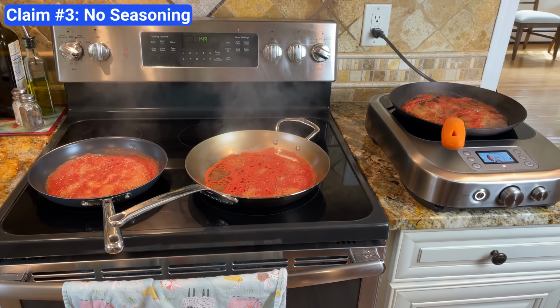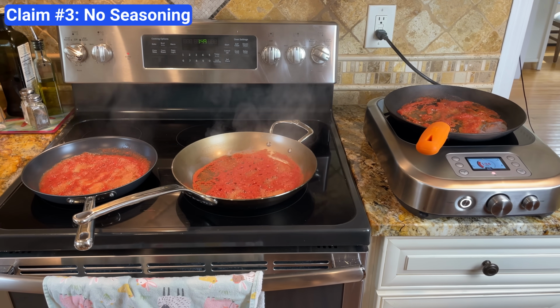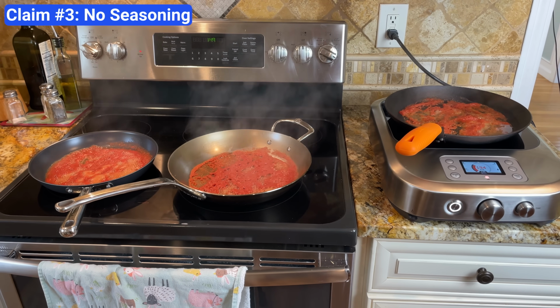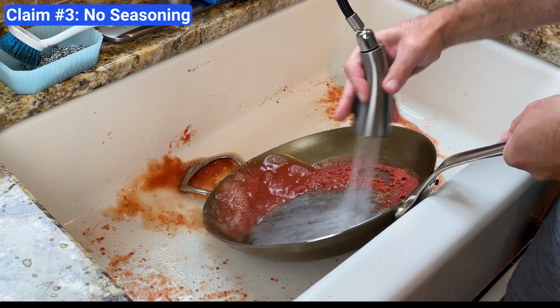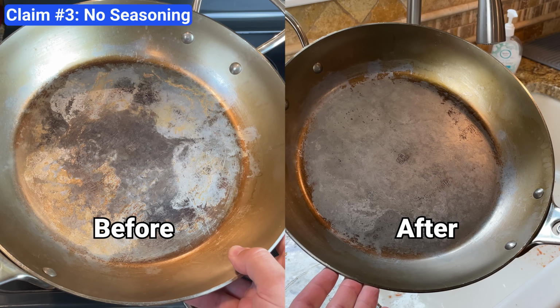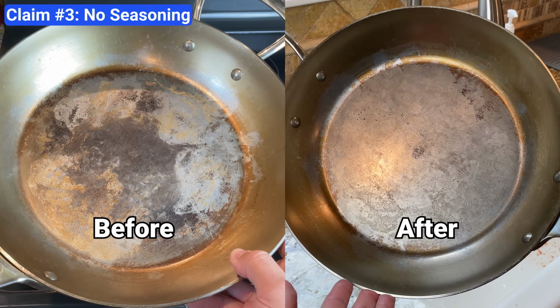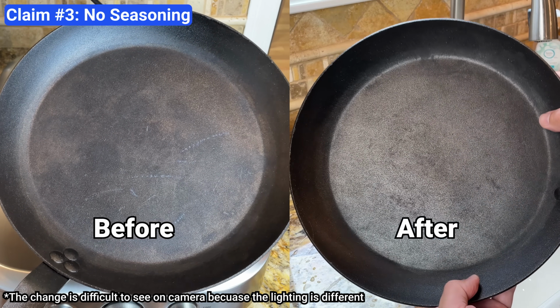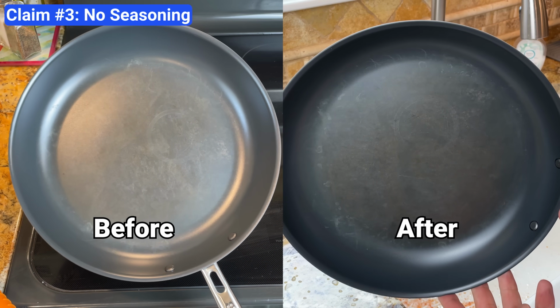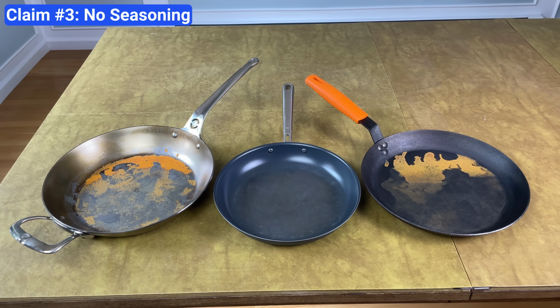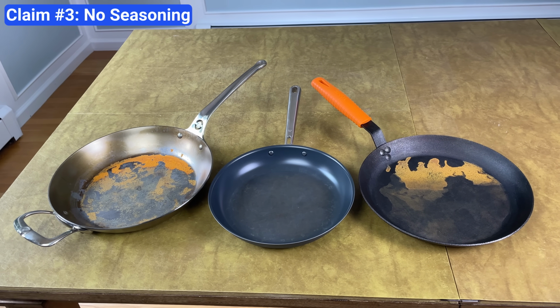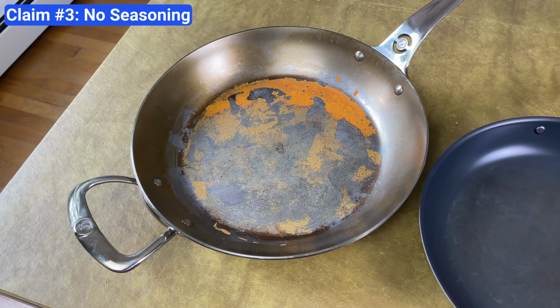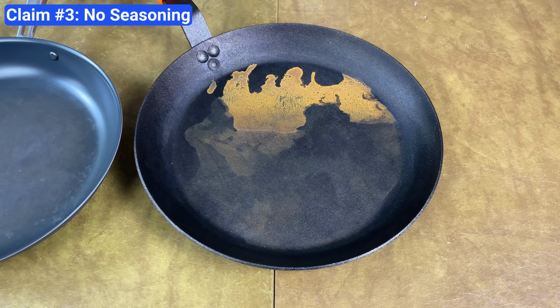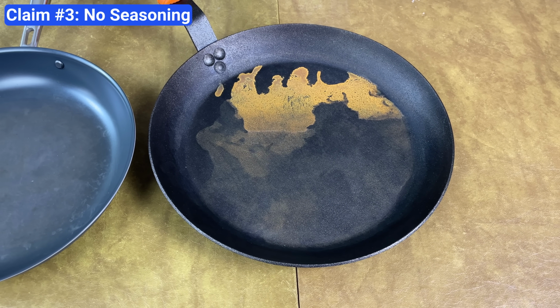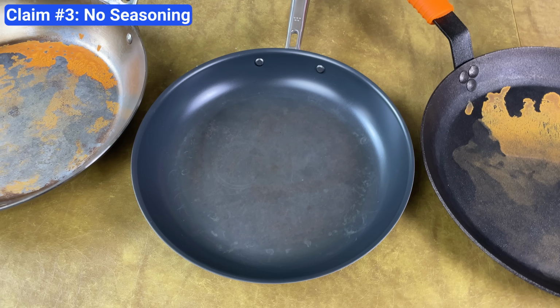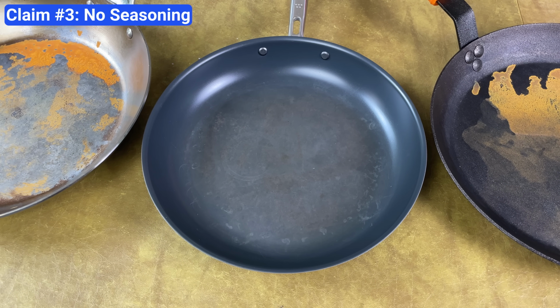To test how each pan reacts to acidic foods, I poured crushed tomatoes in each pan and simmered them for 15 minutes. After rinsing, the seasoning on the De Buyer pan was almost completely gone, and the Lodge looked noticeably lighter. The Misen had no visible change. After that, I repeated the water test and left all 3 pans wet overnight. This time, the De Buyer was heavily rusted, and now the Lodge was also rusted, likely because the tomatoes wore down the seasoning. Fortunately, the Misen still showed no signs of rust.